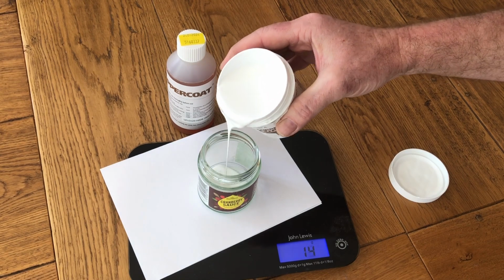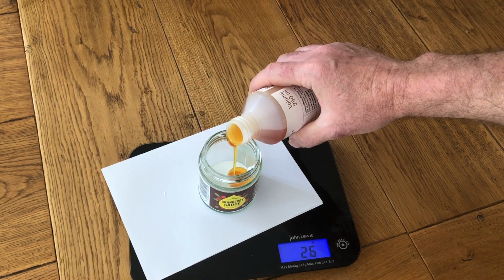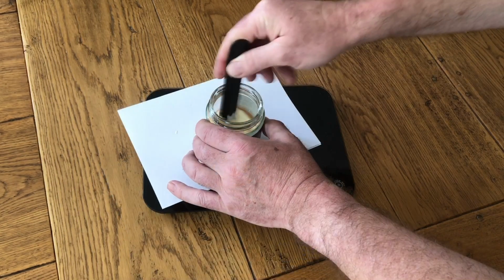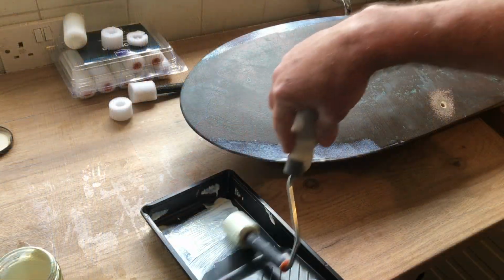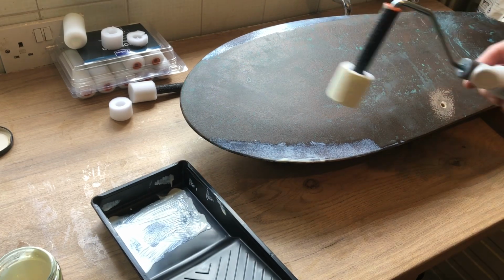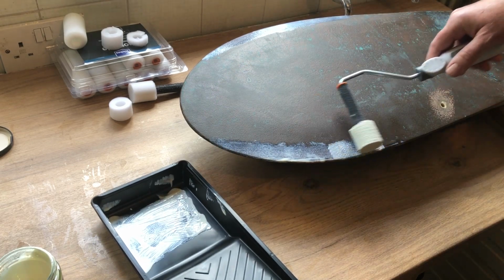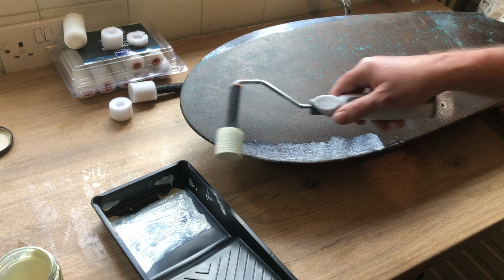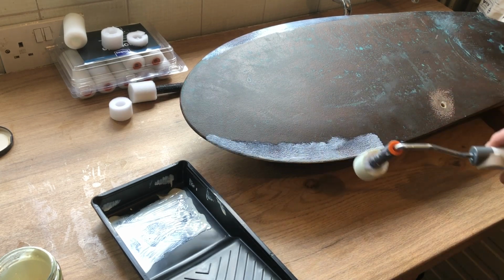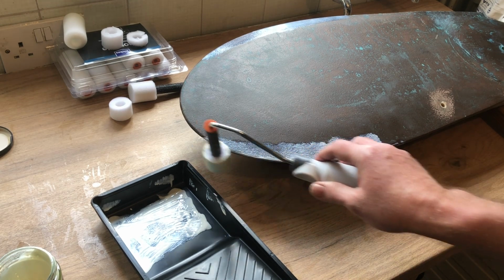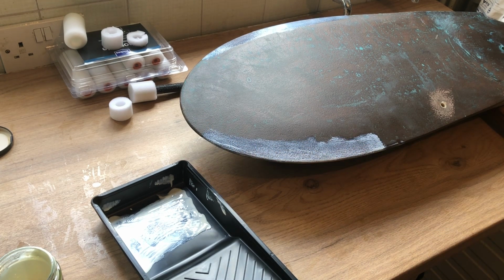This is where the process for reapplication differs from a first-time application. When touching up Coppercoat, the first coat consists of resin and hardener only. No copper powder is added. The second and subsequent coats should be applied while the drying coat is still tacky. How long it takes to become tacky will depend on the thickness of the coat and temperature. At 20 degrees, it will normally take an hour, but keep checking for tackiness.